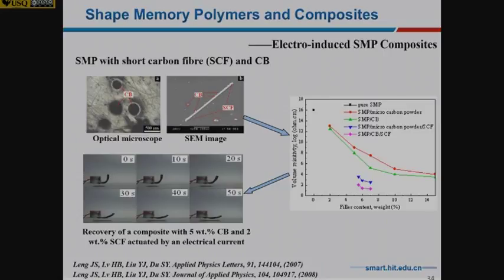So we tried a lot of different conductive particles. I don't want to say everything, but we tried. This one is a short carbon fiber with carbon black. You can see the volume resistivity down to 2 ohm centimeters, which is just 7% of the filler content.